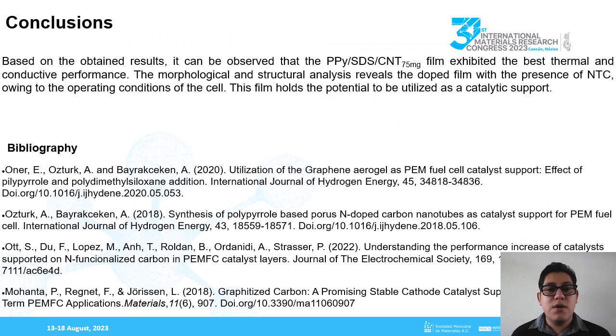As for conclusions, based on the obtained results, it can be observed that the polypyrrole with SDS and with 75 milligrams of carbon nanotubes film exhibits the best thermal and conductivity performance. The morphological and structural analysis reveals the doped film with the presence of the carbon nanotubes owing to the operating conditions of the cell. These films hold the potential to be utilized as a catalytic support.